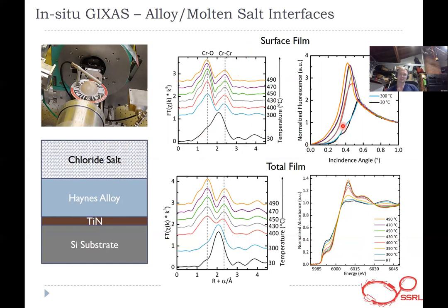We can use what's called an angle curve. It's basically a reflectivity curve over the critical angle, looking at fluorescence to see how the chromium is changing, or where the depth of it is changing as the experiment proceeds. We can also look at the bulk of it by tilting the angle higher. We can look at a bulk-like sample. So you can see the XAS between these two situations is different.